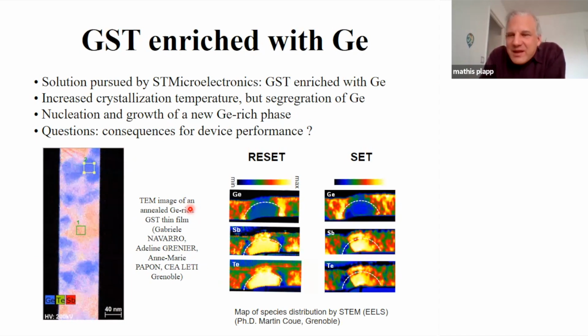There's segregation. When it crystallizes, it rejects germanium into the amorphous phase. And when this rejection is sufficiently strong, that is, when enough germanium has been added to the GST, then you can even have the nucleation of a new phase. So this is shown here in the left picture. It's a TEM picture of a thin film that was amorphous in the beginning. It was just baked, so annealed. And you can see here the color code. Blue is the germanium atoms, green and red are the others. And you see that there are regions that are very rich in germanium.